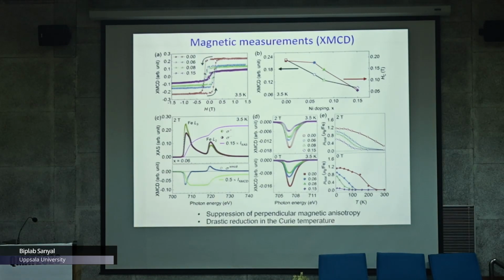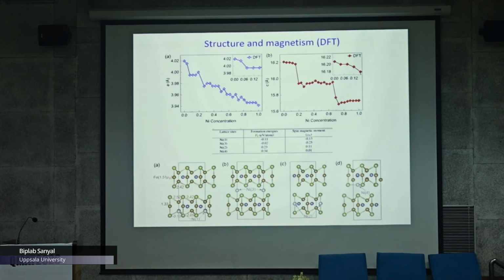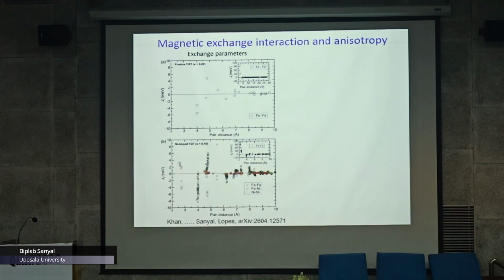Now the question is, why does it happen like that? So they came to us, and then we did a lot of calculations to simulate this alloying part. And basically what we see is that the a-axis and the c-axis lattice parameters also change with nickel concentration. And all the local properties, like local magnetic moments and things like that, were extracted. But the important part is actually the magnetic exchange interactions.